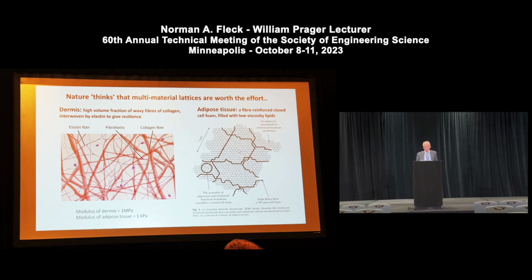In contrast, and we've all got this, above our fat cells lies the dermis. The dermis is a collagen network. It's a multi-phase collagen network. It's primarily collagen fibers, high volume fraction. They're wavy. Collagen itself is very stiff, stiffness of titanium, and it relies on the waviness of the collagen fibers in order for the modulus of dermis to be about a megapascal, same as that of rubber. So that's how we can move around. It's a fact, and we've measured it.